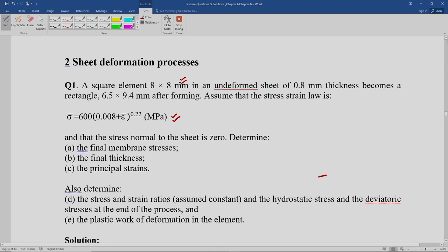So, a square element, we say 8 by 8 mm, is going to become a rectangular element of this particular dimension. Whenever you say rectangular element, the larger value will go to length, isn't it? 9.4, and this will be given by 6.5. So, basically you are pulling it on one side, say for example, so it gets compressed on the other side. So, 8 becomes 6.5, 8 becomes 9.4. Initial sheet thickness is provided to you. Now the question is,